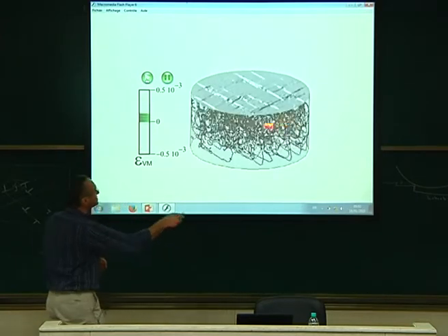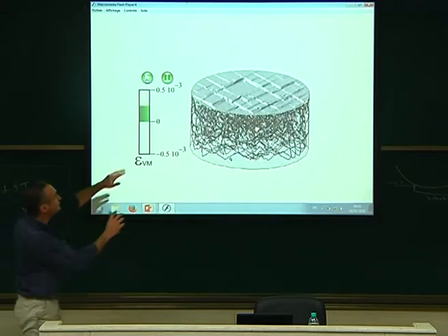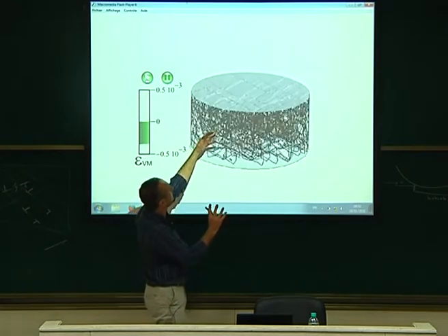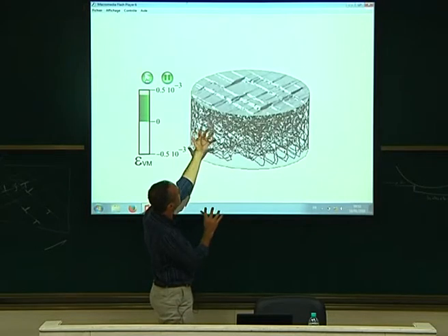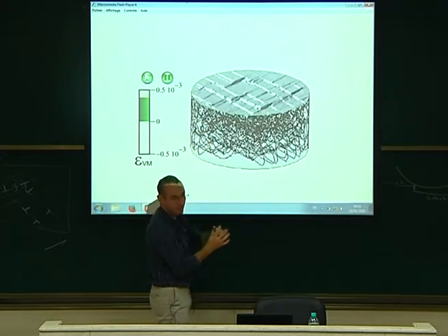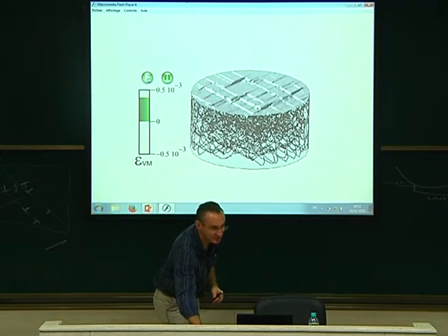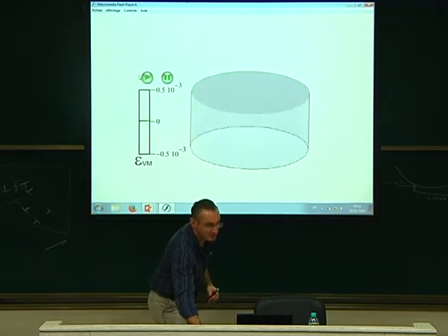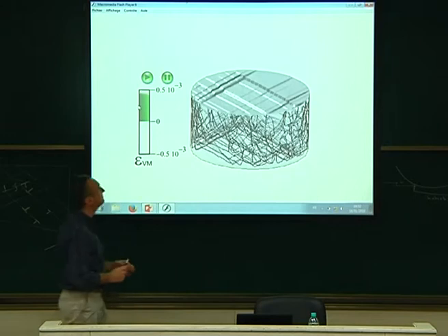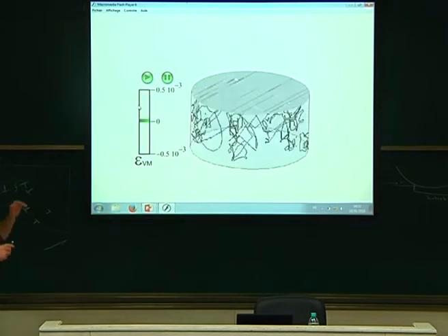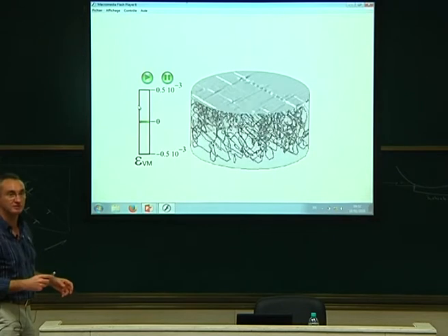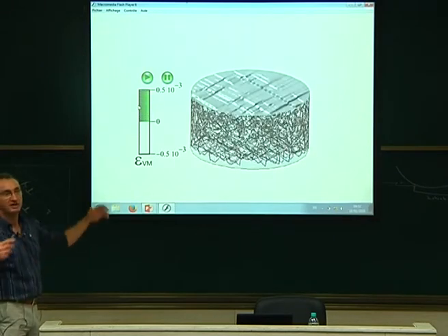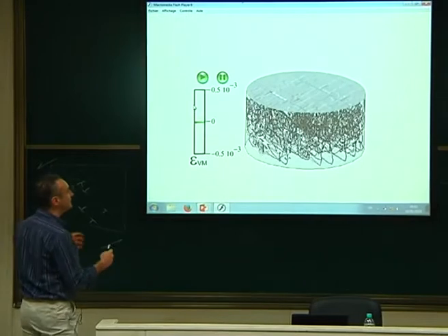So you can see a huge dislocation density forming. You can see also how the shape of the volume is changing. You can see that I'm loading one way and then the reverse way and so on. I can play again because I think this movie is quite nice. Okay, I play again. Poof, cross-slip, dislocations everywhere. This is good from the material point of view because it means that now the plasticity is homogeneous. If it's homogeneous, you can sustain a large life. You have a big life.